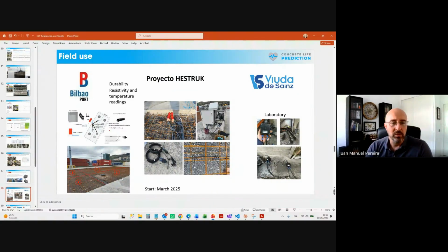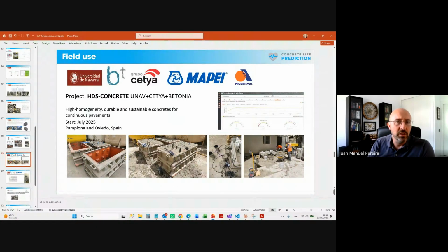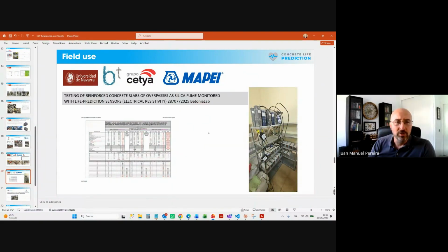Also, with new binders, with high replacement of the clinker with supplementary cementitious materials. And the port is really interested in these things because when they demolish a structure, they need to know if they can recycle it or not and how that affects that. And especially in ports, having 100% uptime is really important. And these are other types of investigation with universities in Spain and different companies, okay, experts in slabs, for instance, and polished floors, like an Amazon warehouse, okay, for logistics. Okay, so we did a lot of tests with this.